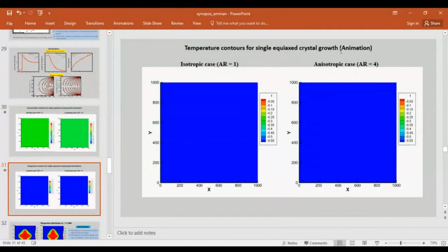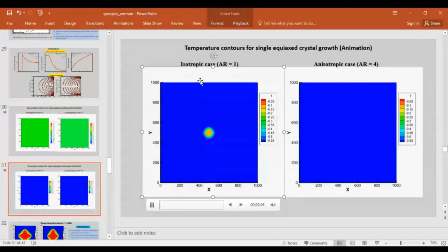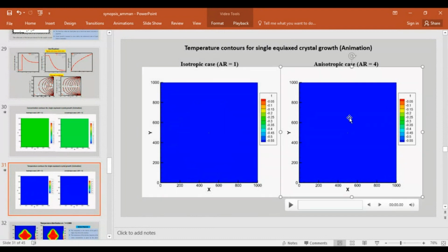For the single equiaxed crystal growth, this is our temperature distribution. Why it happens, we will discuss. Here we are getting a uniform growth. But for the anisotropic case, we are getting a non-uniform growth. Now we can see.